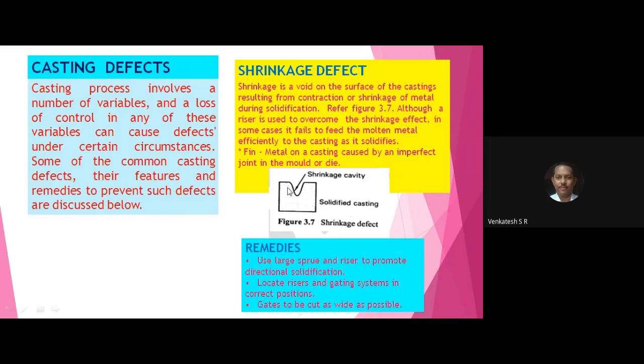where there is a shortage of liquid metal. The only point is that shrinkage defect arises in the casting only due to the shortage of liquid metal. As I told you earlier, if you provide the riser perfectly in the mold cavity, it supplies the liquid metal into the mold cavity so that you can avoid shrinkage. It compensates the shrinkage of liquid metal and supplies a little amount of liquid metal into the mold cavity so that there is no shrinkage defect in the casting. If there is a shortage of liquid metal, it makes a shrinkage cavity or wide hole on the surface of the casting.